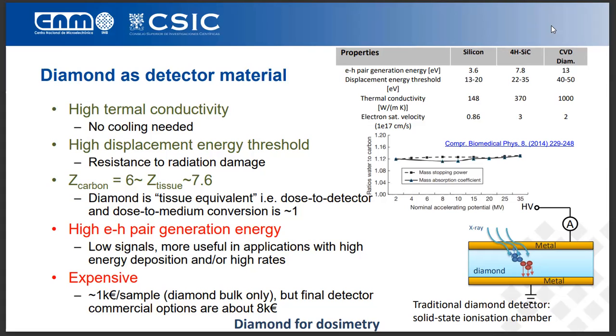So this is how a typical traditional diamond detector looks like. It's basically a solid state ionization chamber. You have your material, in this case diamond, sandwiched by metal electrodes with which you apply an electric potential. And when ionizing radiation gets into the diamond, it generates electron hole pairs, and to collect the charges, actually, the current is induced by the drift of the charges. This is a technicality, and you get a signal.